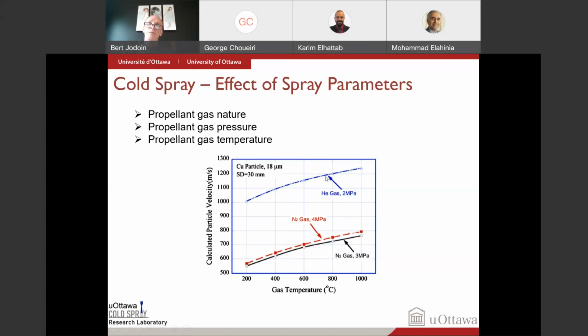If you switch to helium, oh, that's great because now helium is a lighter gas, has a much higher speed of sound, and you can see that the particle will accelerate much faster. However, helium is very expensive and it's a non-renewable resource compared to nitrogen. So despite the fact that we get better performance using helium, we tend to stay away from helium because it's too expensive and not a renewable type of resource. So we spray using nitrogen or air.